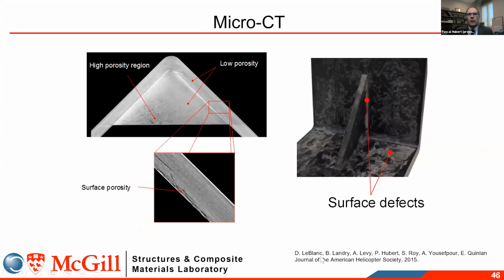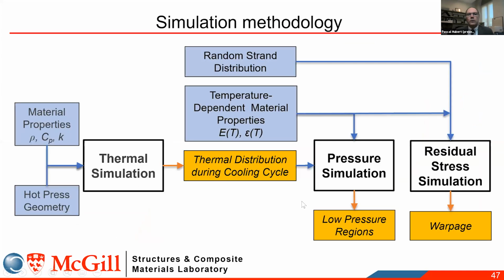You can control the heat from the top and bottom mold, but sometimes you don't know how to control it properly. So what you end up with are regions of high porosity, because at some part during the process, you lost contact with the mold and you had not enough compaction pressure. And the more complex the part is, the more it's going to be difficult to maintain this. So you need some tools to do that.